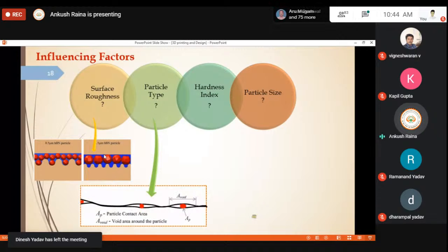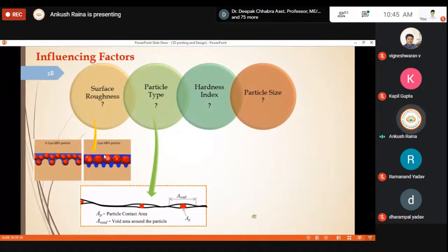Secondly, the type of the particle, whether the nanoparticle which we have used is hard in nature or soft in nature. If it is hard in nature, it will not deform, it will have a rolling action. But if it is a softer particle, it will try to deform. We have different soft materials like hBN, WS2, hexagonal boron nitride, tungsten disulfide, and molybdenum disulfide. These are soft materials, and these form a layer by layer structure. So the type of particle will also govern the overall behavior of these sliding components.